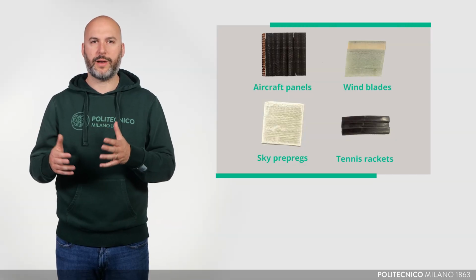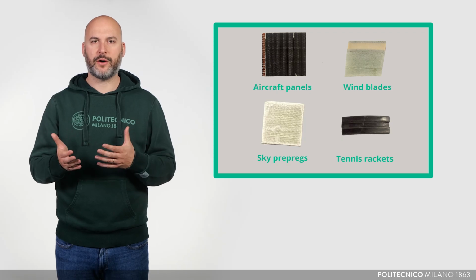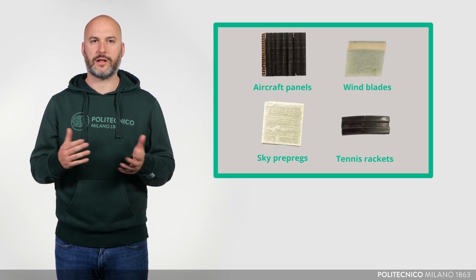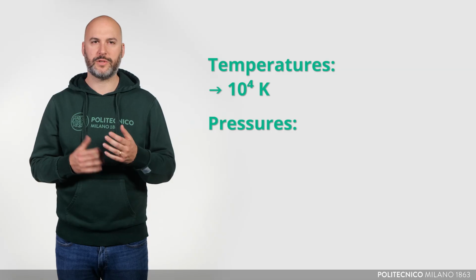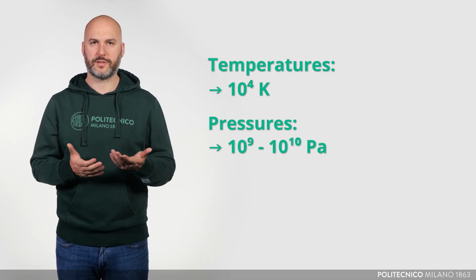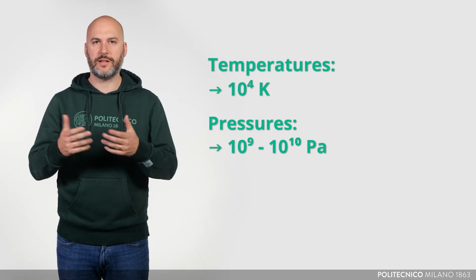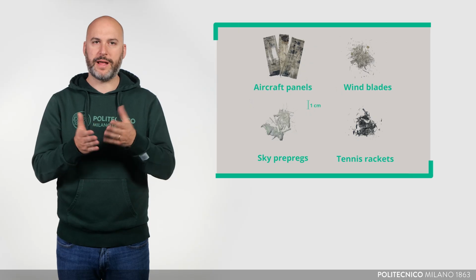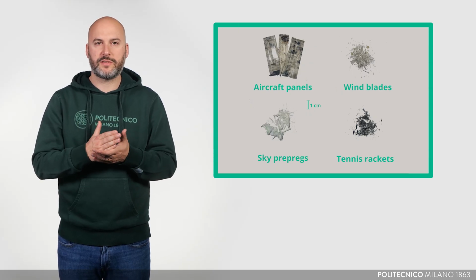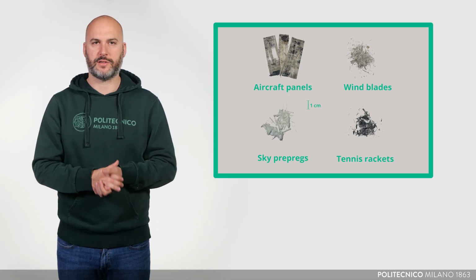When the current ramps up within a time span of less than 500 nanoseconds, a plasma channel arc is generated between two electrodes. This plasma channel targets the solid sample placed for treatment, as the dielectric breakdown strength of solids is lower than that of the surrounding water medium. Temperatures around 10^4 Kelvin and pressures ranging from 10^9 to 10^10 Pascal are produced, creating localized shock waves within the solid sample. These shock waves propagate through the solid, focusing on weak spots located at the phase boundaries. This allows us to obtain recyclates that are of better quality than those recycled mechanically, at process costs that fall between those of mechanical and thermochemical processes.